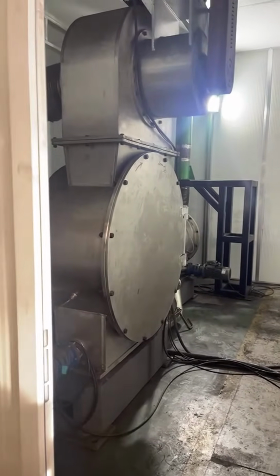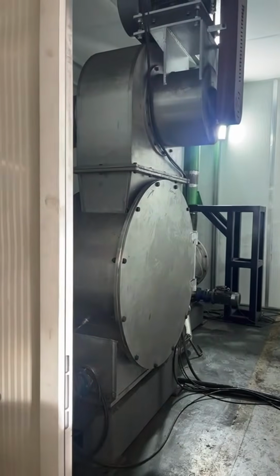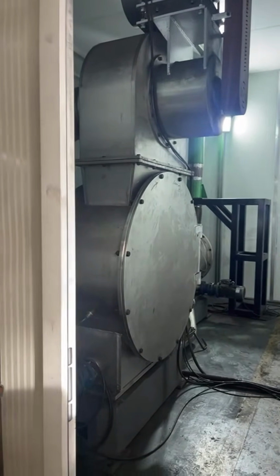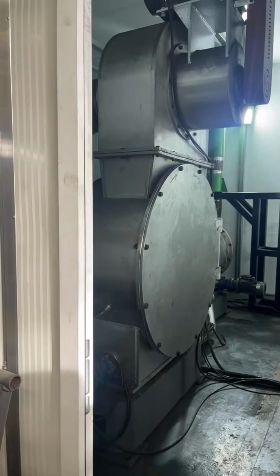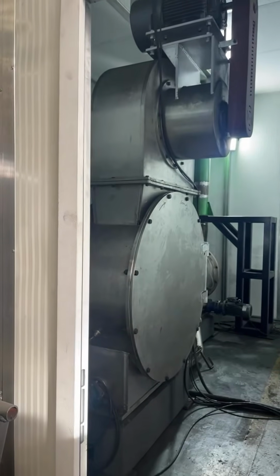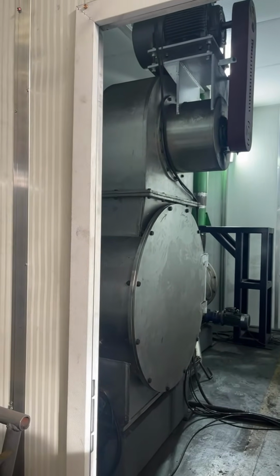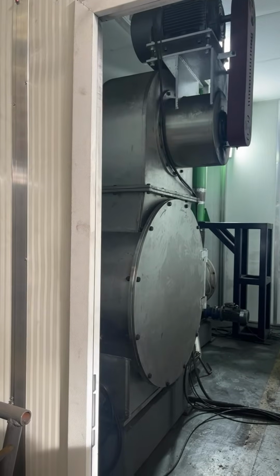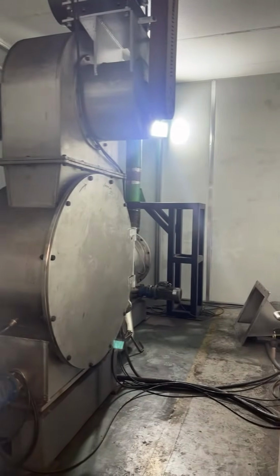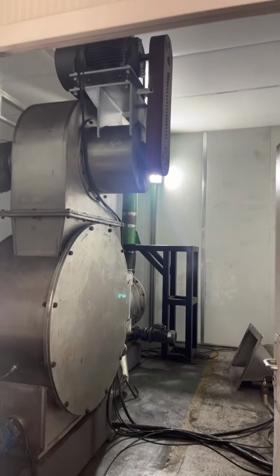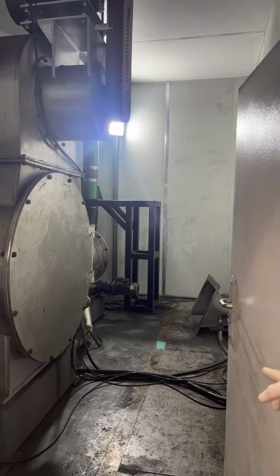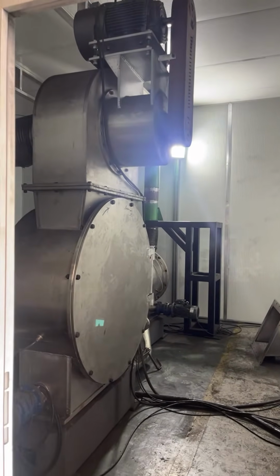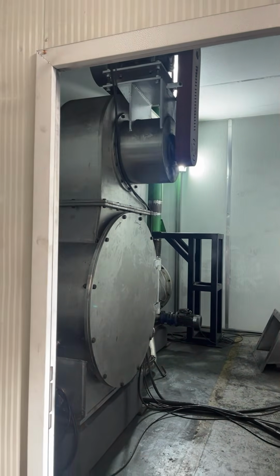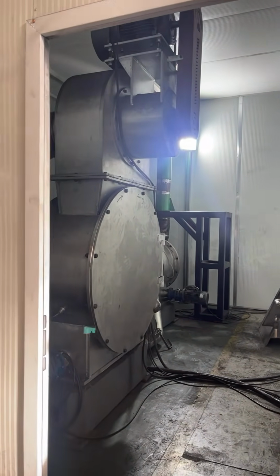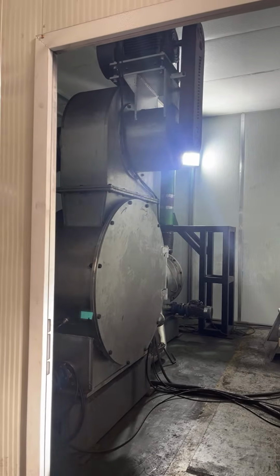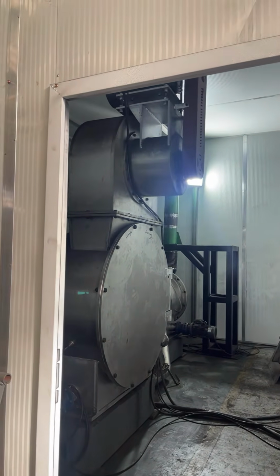And during the crushing process, you can understand black mass is a kind of powder, and it is bonded on the copper and aluminum. By the crushing, the powder will fall down, and then they will fly up. They will follow the green pipe, and then the powder will fly up. But the copper and aluminum will come down and then enter the next system. By this crushing, we will separate the black mass, and the black mass recovery we can reach more than 95%.